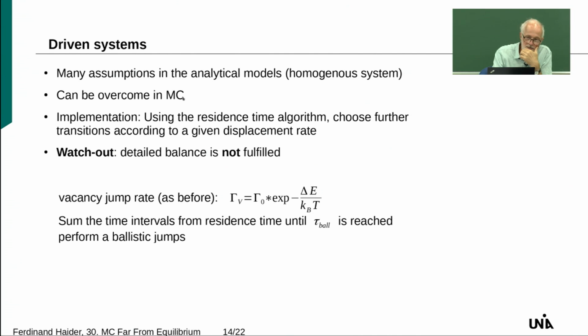So what I did is I put down a Monte Carlo code, and besides our thermal jumps with a vacancy, once in a while I do a forced exchange. And regarding these kinetic equations, it's obvious. I just add this probability for athermal exchanges. Okay?